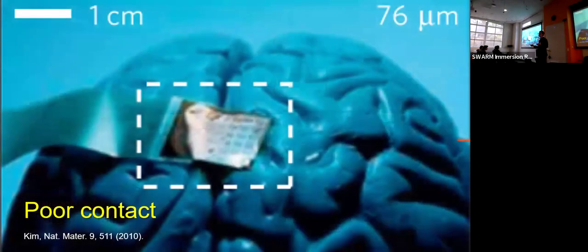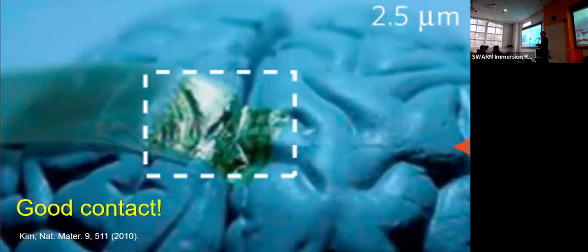This concept was clearly proven by Professor Dae-Hyeong Kim and John Rogers almost 15 years ago. Dae-Hyeong fabricated this inorganic-based TFT system onto polyimide films, plastic films. When they used the 76 micron thick polyimide films, there was a poor contact between the device and the brain surface models. But when they decreased the thickness of the substrate down to 2.5 micron, they could make a very good contact between the devices and the brain surfaces. Because the flexural rigidity is dramatically reduced, the devices can be easily bent, as shown here, and they conform to the wrinkled surfaces. This is a very important aspect of why we need to reduce the thickness of the devices.